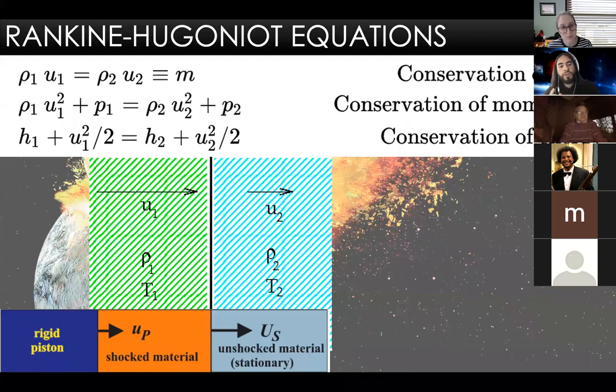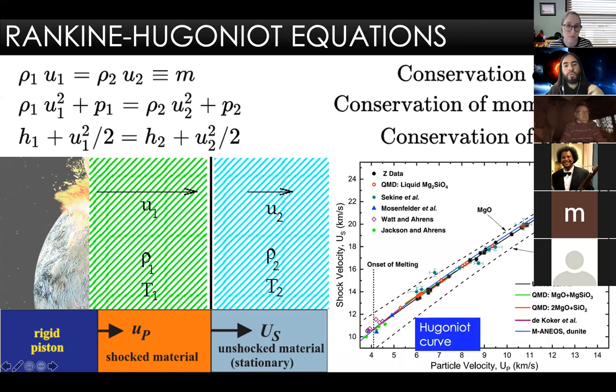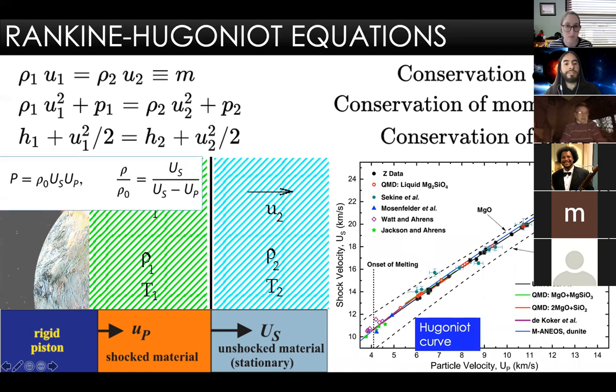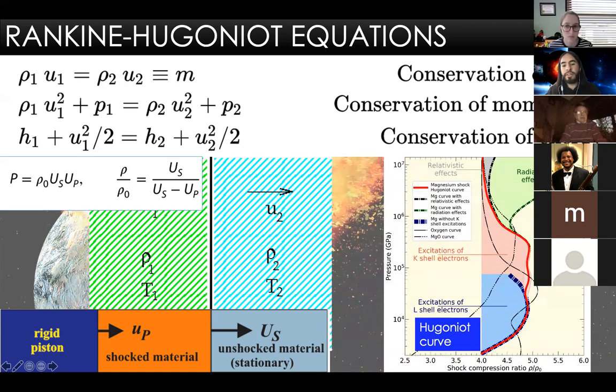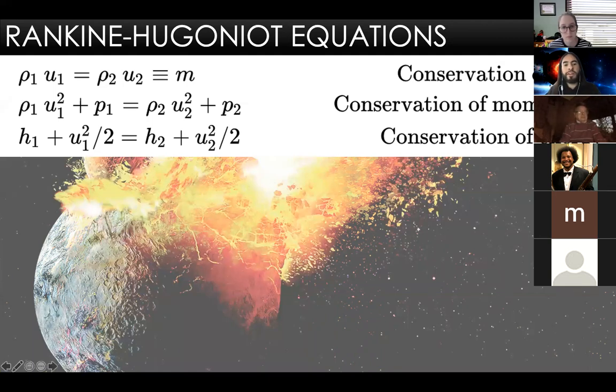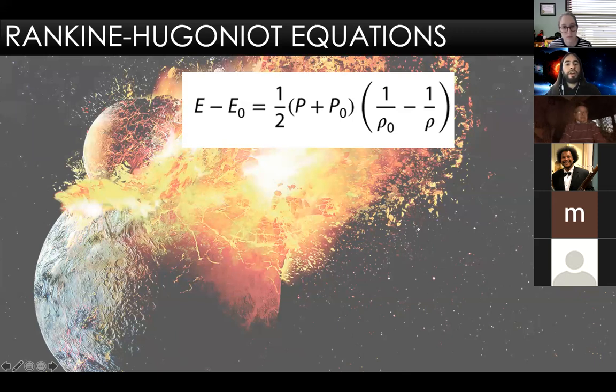So when you generate a shock wave, we actually have physics behind this that allows us to understand these states better. We have conservation equations that allow us to understand what happens with the matter after it's been shock compressed. And we put these states in a line of shock velocity versus particle velocity, again, which is called the Hugoniot. But using the physics behind these processes, we can convert this into pressure and density and generate this from simulations. So we can generate the Hugoniot curve from simulations and predict what an experiment will observe when doing these shock compressions. So we do so by simplifying this equation into a more simple energy equation that we can solve once we perform simulations of matter at extreme conditions.